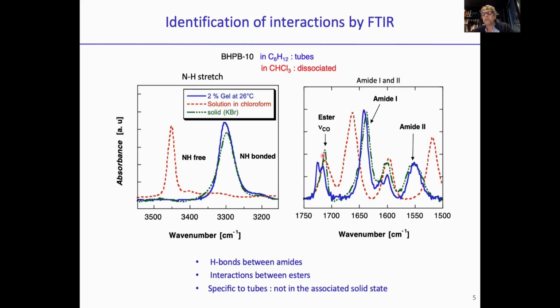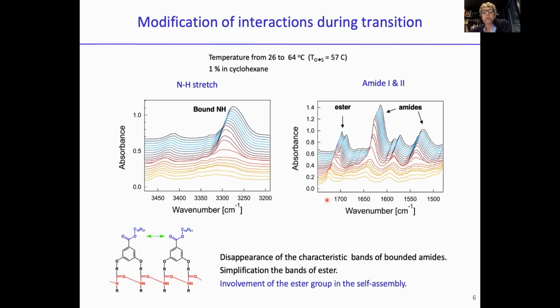In the powder, when everything is associated, you have a single band, but the nanotubes have a special design with a double band here for the CO stretching. So this shows that we have a kind of special interaction between the esters. This is confirmed by variable temperature experiments. We took the solution of tubes and heated it until it dissociates, and you can see that all the characteristic bands of the tubes tend to disappear, including the ester. The conclusion is that in the solvent, all the amide groups are held together by H bonds between the amides, and we also have this interaction between the esters.